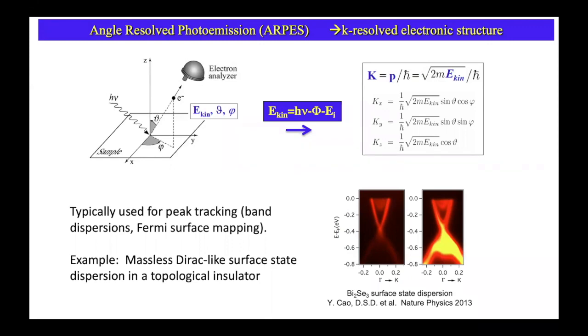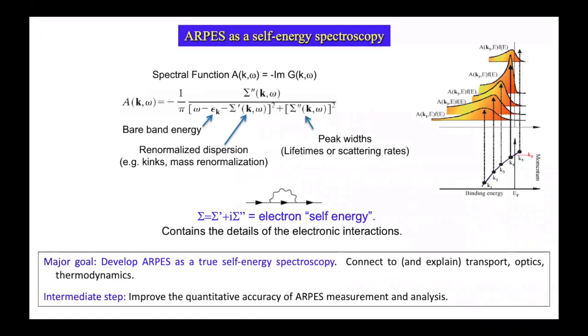We've been working very hard over the last number of years to go much beyond that, to really get at the band broadening and band renormalizations, and all this is contained in the spectral function. And for this group, you're very familiar with this, really it's about the self-energy, sigma prime and double prime, the real and imaginary parts. Basically, the imaginary part broadens it, the real part shifts, or renormalizes, the band energies.